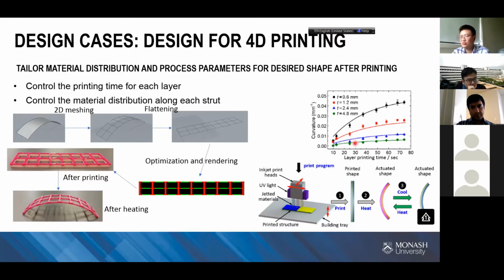And we also found the residual stress is not only caused by the materials, the actual residual stress will also differ based on different printing process parameters. Layer printing time will also affect the residual stress. So we do the optimization for both material and process parameters to control the shape.